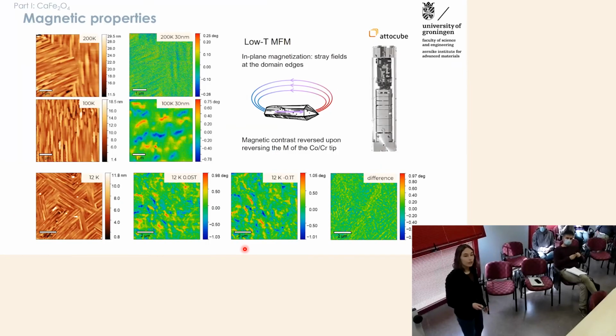And then we also investigated microscopically the properties of these films. We have this interesting MFM instrument in our lab that allows us to measure MFM at low temperature. We can first measure the magnetic signal above the Néel temperature, for example at 200 K, and as you can see here, there's almost no contrast in the phase of the MFM. But when we cool down below the ordering temperature of this material, we can actually see some magnetic signal coming out. Now you can probably argue, but you just said that the easy axis of this material was in the plane of the film. So how do we actually see some MFM magnetic contrast, which is usually only out of plane?